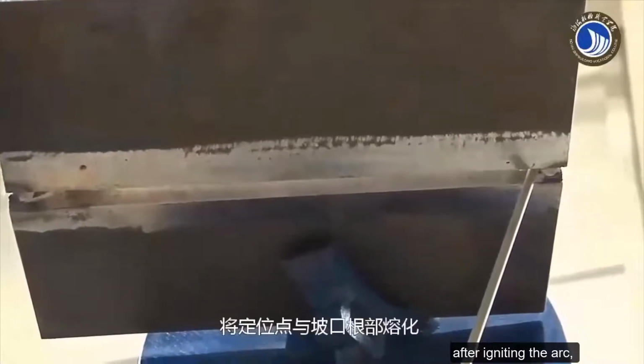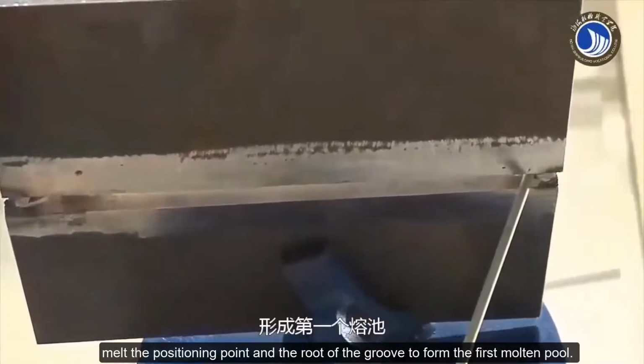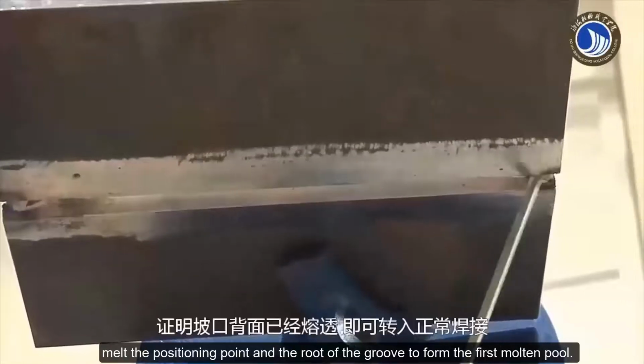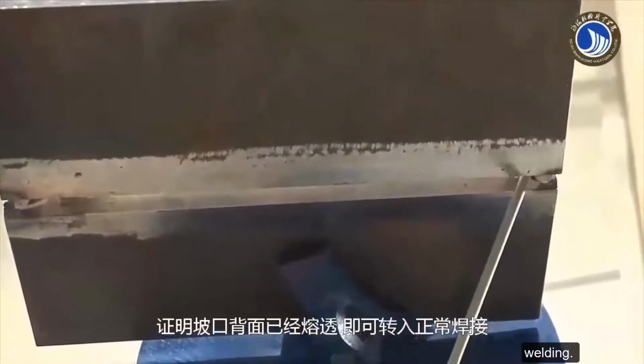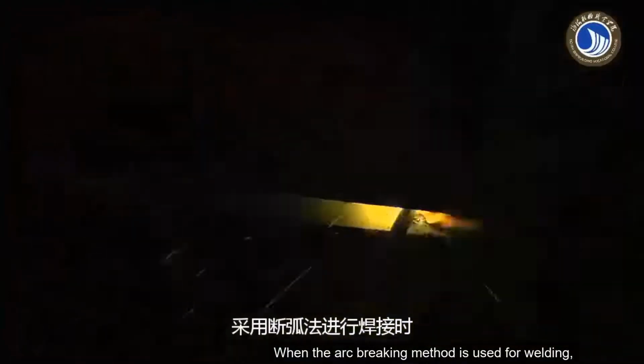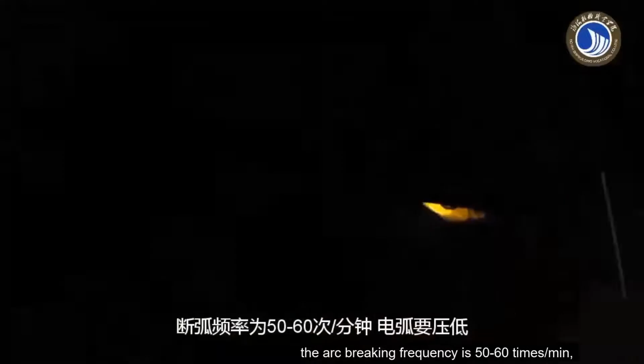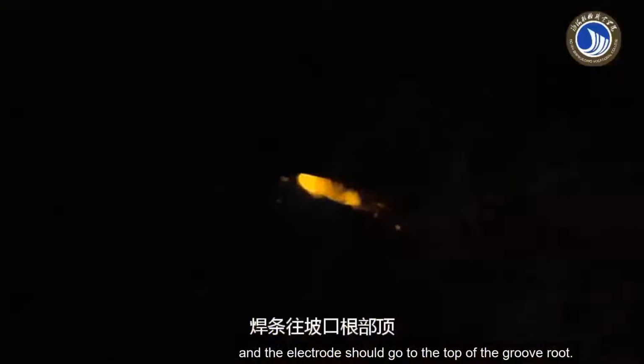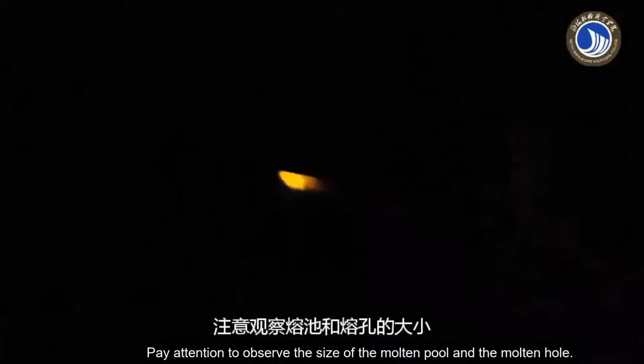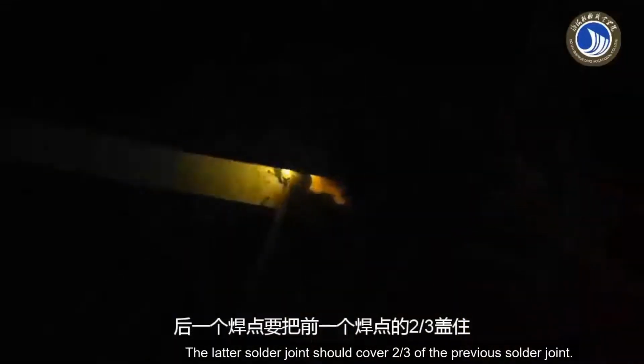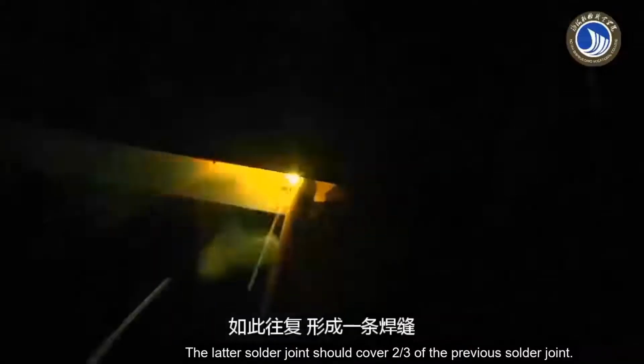After igniting the arc, melt the positioning point in the root of the groove to form the first molten pool. Welding. When the arc breaking method is used for welding, the arc breaking frequency is 50 to 60 times per minute. The arc should be lowered, and the electrode should go to the top of the groove root. Pay attention to observe the size of the molten pool and the molten hole. The latter solder joint should cover 2/3 of the previous solder joint. In this way, a weld is formed.